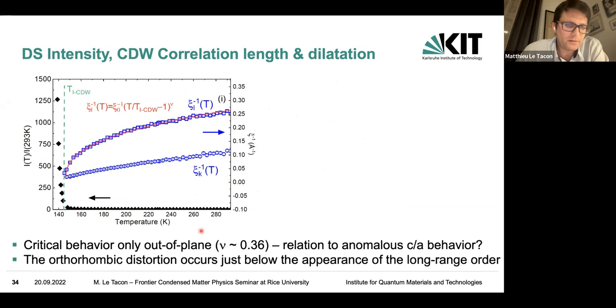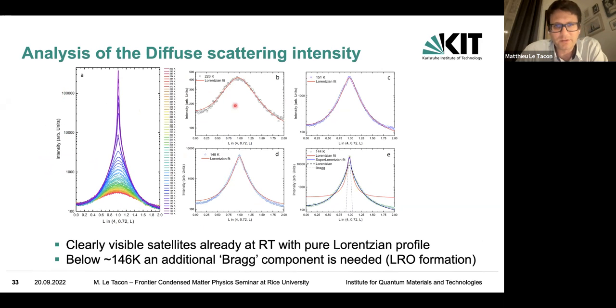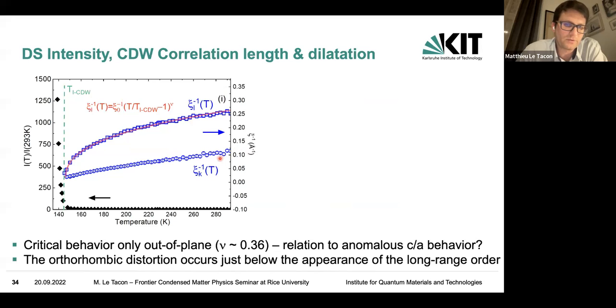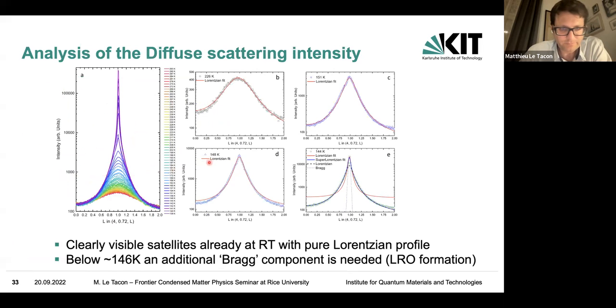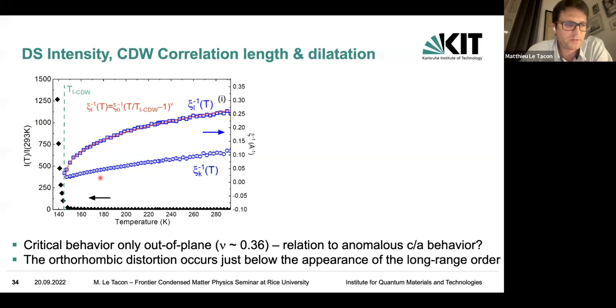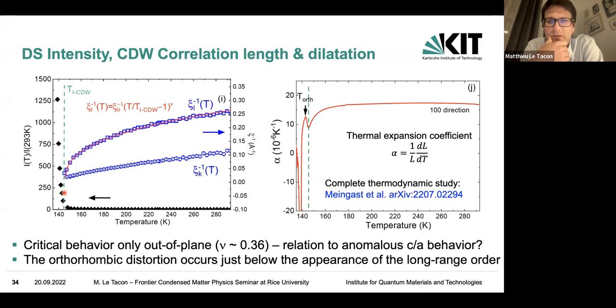So we could analyze this very nicely. The width of that Lorentzian is inversely proportional to the correlation length. What you find is that the in-plane correlation length is increasing slowly as you get towards low temperature, but it's not really critical, I would say. It's almost linear, in a kind of funny manner. But along the c-axis, the inverse correlation length increases much more dramatically and exhibits some kind of critical behavior. And if you look simply at the peak intensity, you find that it shoots up pretty much at the temperature at which the correlation lengths along the c-axis tend to diverge and corresponds to the long-range order, which relates to the anomalous c over a behavior that Christoph sees in the thermal expansion.